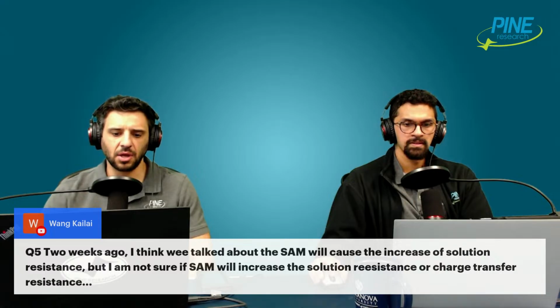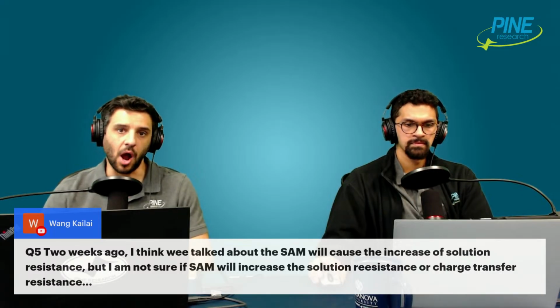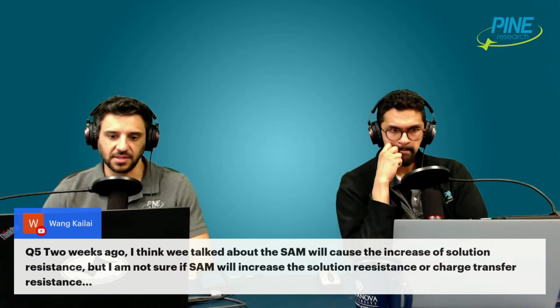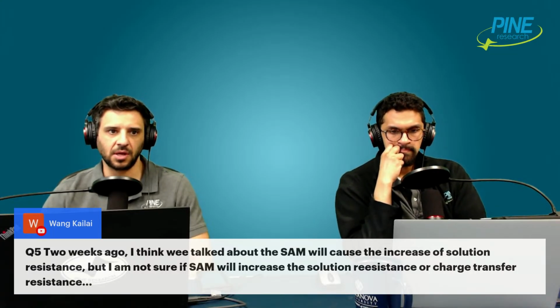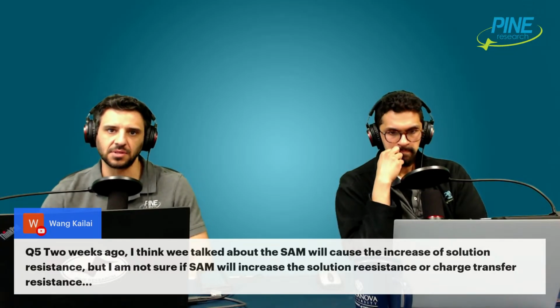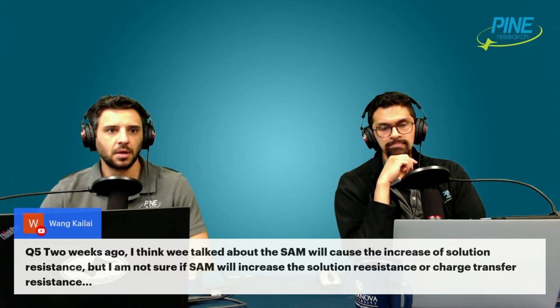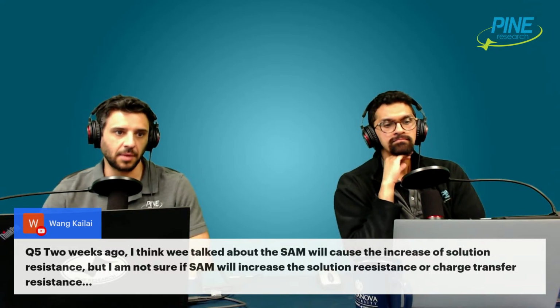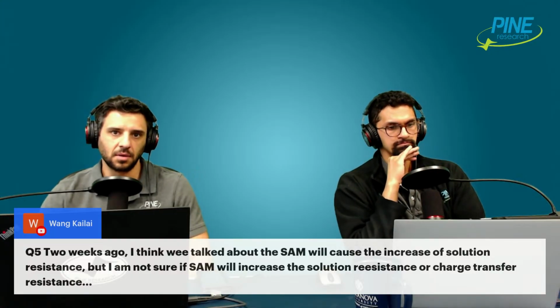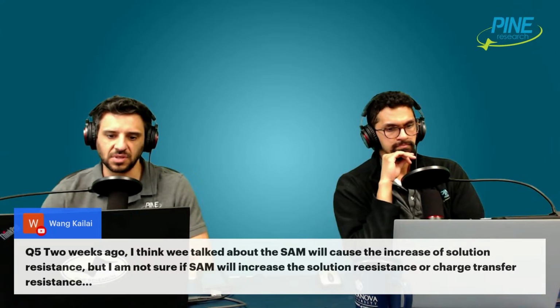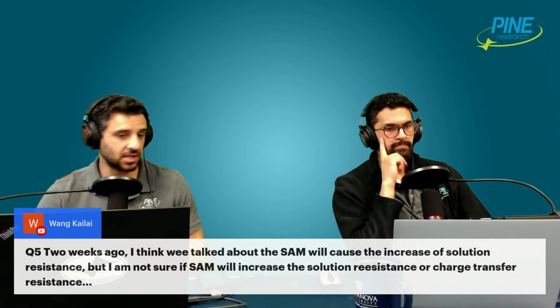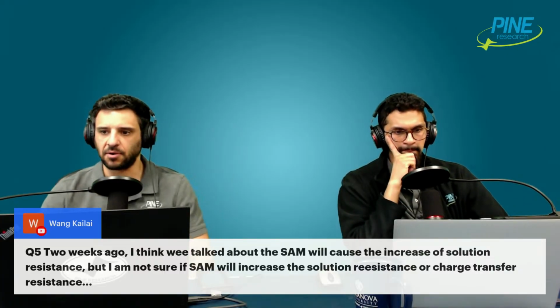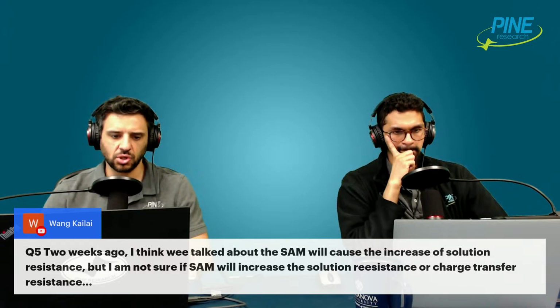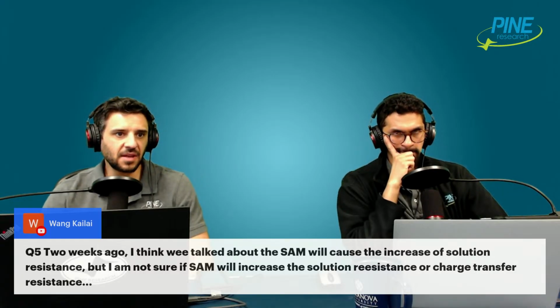It could increase the overall uncompensated resistance. If there's an electrode and you have a monolayer on top of it, it won't affect the electrolyte itself necessarily, but it would increase the ohmic uncompensated R_S, the leading resistor, just because there's another barrier. So it's the intrinsic resistance associated with the electrolyte plus the resistance of the monolayer. If that's what you mean by increasing the solution resistance, I think that's right, because it's like you've drawn before, a sum of two resistors. So it would aggregate to make it bigger. But will it increase the charge transfer resistance? If it participates in the kinetics, I suppose.